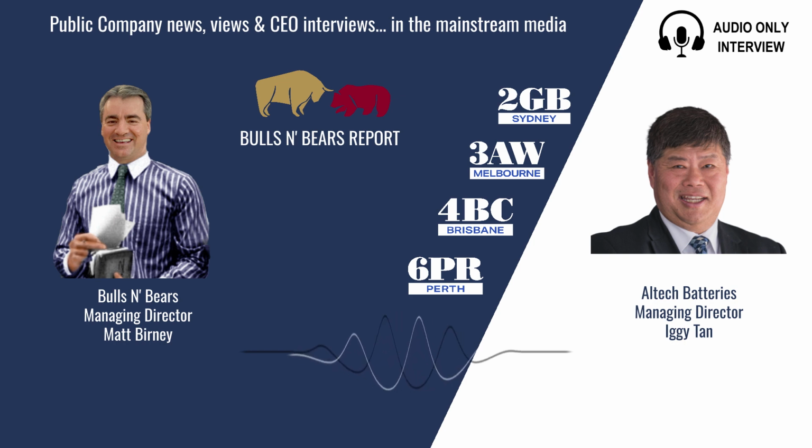So tell me about the specific battery performance benefits you hope customers will get by using silicon in their anodes. So we recommend a 10% mix into the graphite and the anode part of their batteries, and that should give at least 30%, a minimum of 30% extra energy density for their lithium batteries.